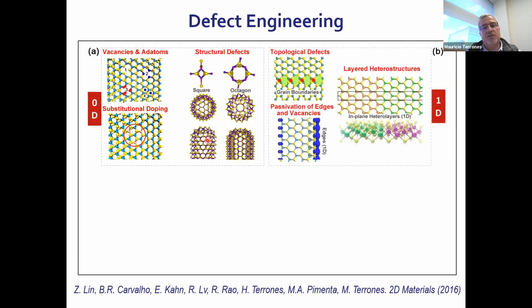And you have the one-dimensional defects, which are the edges of these structures that can be passivated or functionalized, but the edges are very active. You also have grain boundaries. For example, you can have this octagon-square sort of grain boundary in these chalcogenide monolayers, or you can have in-plane heterostructures. So you can stitch together a moly sulfide with a tungsten sulfide monolayer, and they're in the same plane, and you have these one-dimensional channels. So here you have all these one-dimensional channels, which are very interesting as well from the physics point of view.